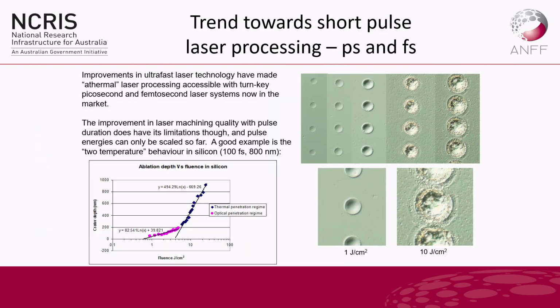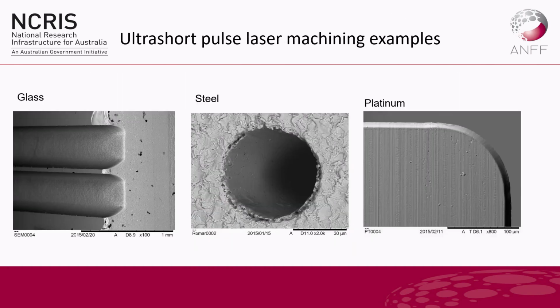I have one example here showing that there are limitations to this, though. This is shooting silicon with a femtosecond laser. You see at low energy that the little shots that we're making, they're nice and smooth, but once we get to a certain energy, we do start to generate some molten droplets. So you can't always push this to very high energies and very high removal rates. You have to be mindful of what's going on.